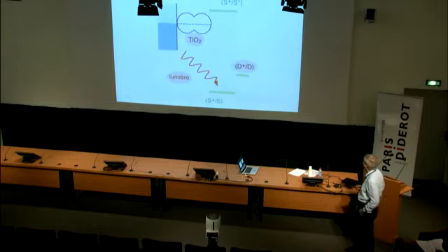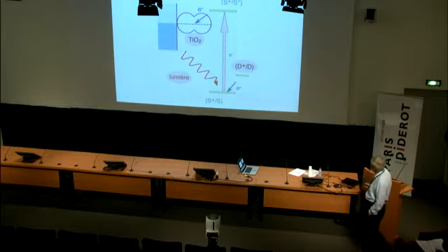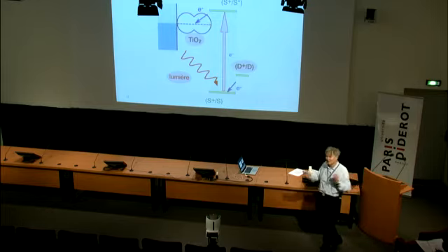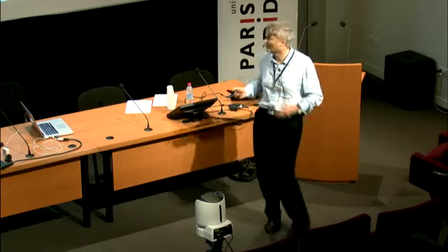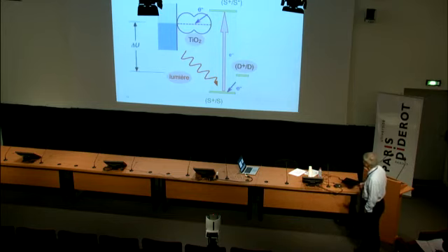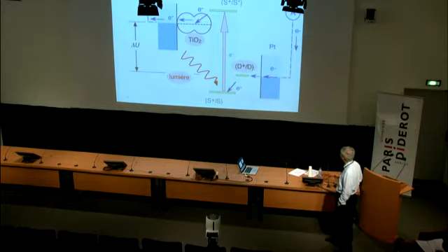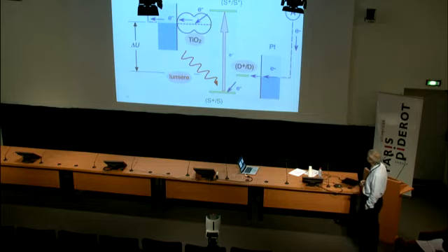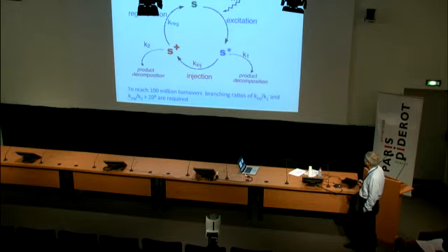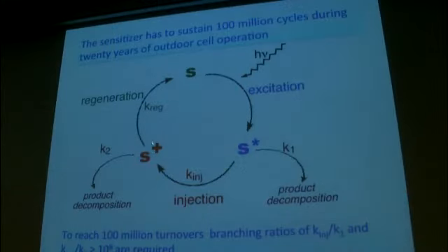And so just to say that again, in French, you have the excitation and then the injection and regeneration of the dye. Now we have separated the charges across the interface. So positive charge is now with the hole conductor and the electron in the film, and that sets up a potential difference. Actually, this is a fairly strong potential difference. It produces a Stark effect on the absorption of the dye. But if you now connect the two sides, you get a photovoltaic cell that works as a regenerator for the electrochemical device. So the dye gets excited, ejects an electron, gets regenerated.